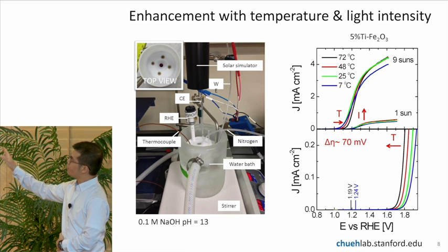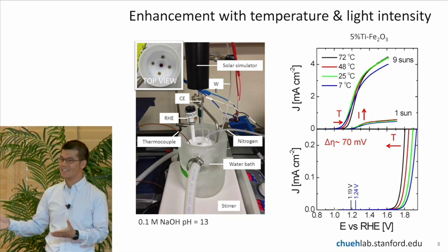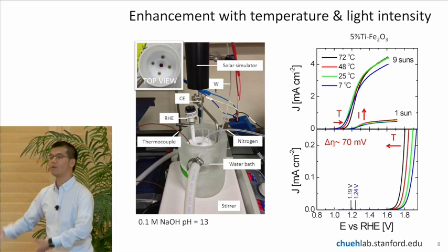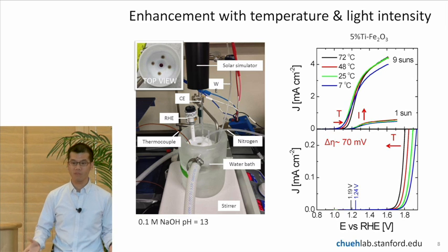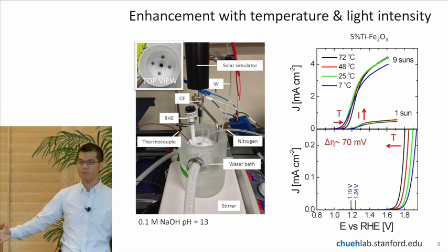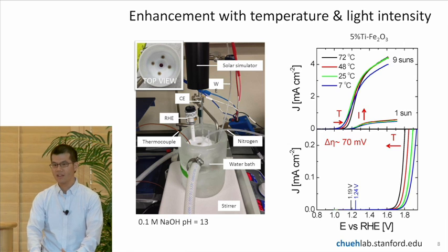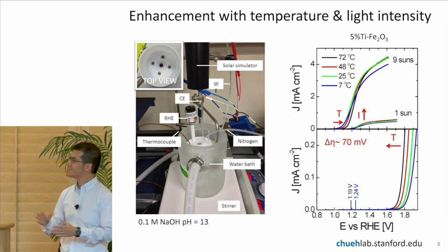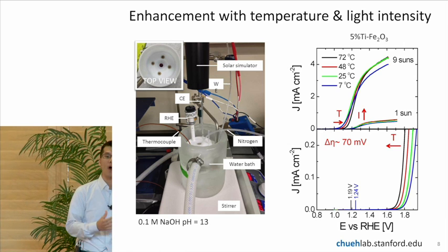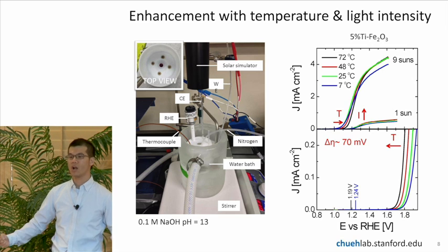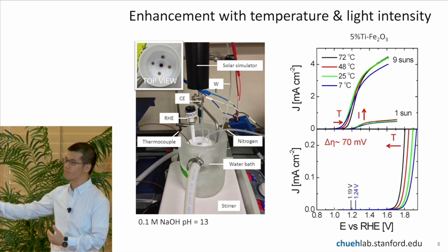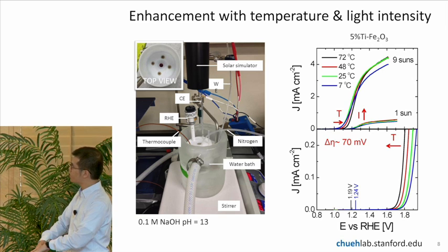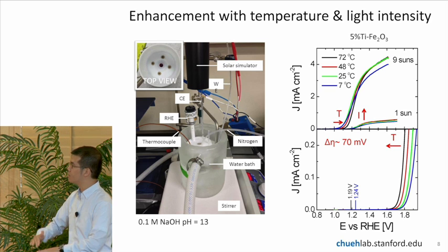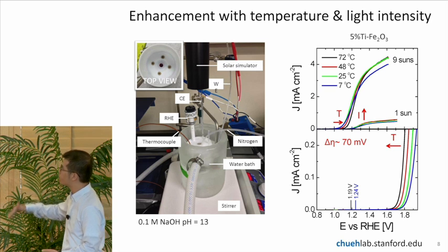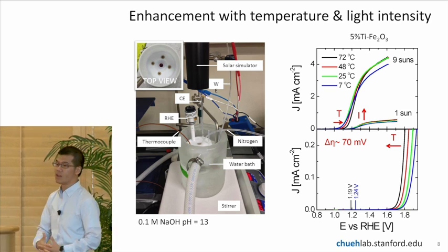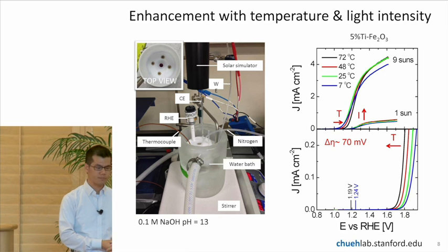So if you look at the plot on the top, as you increase the intensity of the sunlight, the current goes up proportionally. So this is great news. This means we're able to shrink down the size of the cell and still achieve the same current. This doesn't happen everywhere. Depending on how good the material is at separating charge, you might not get a 1-to-1 improvement. So here, when we increase the optical concentration, we have a corresponding increase by 9 times in the current, thereby achieving something that's quite nice.